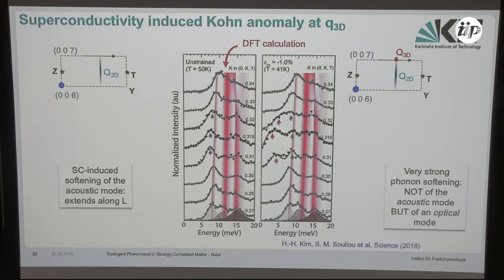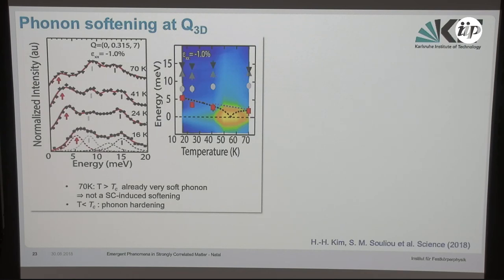But there's another mode, the one I mentioned earlier, that softens. So it must be an optical mode that is getting completely soft and is associated with the formation of the 3D charge order. That's the temperature dependence here. I had to add a second line because the referee said it could get completely soft, but it could also just monotonically harden across the 3D wave vector. Well, I cannot prove the contrary, but I'm very convinced it's a complete softening of the mode, which is associated with the formation of the long-range charge order.